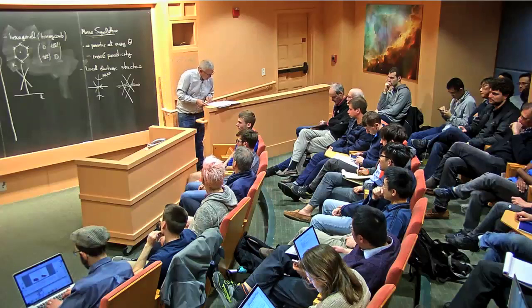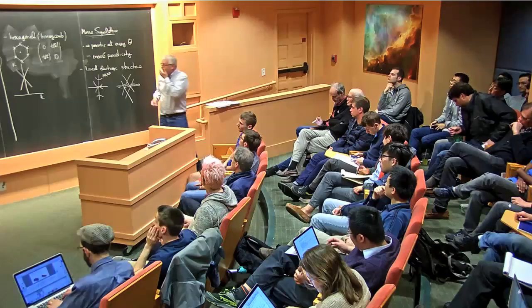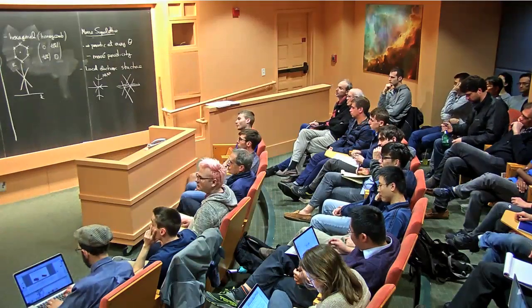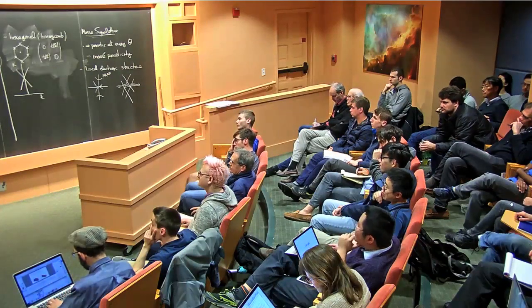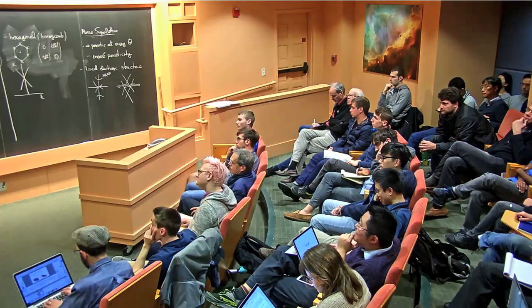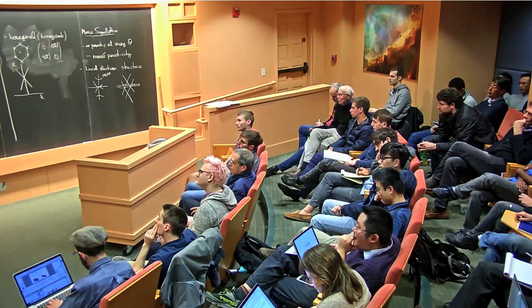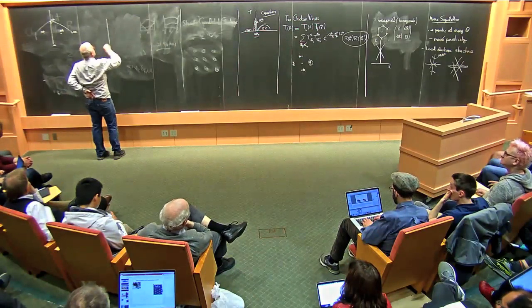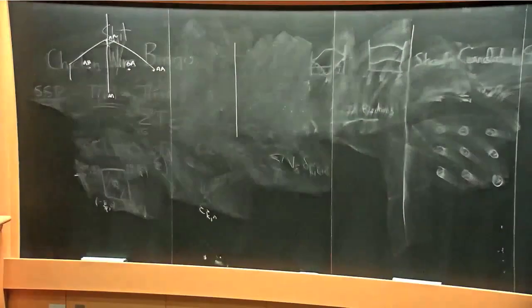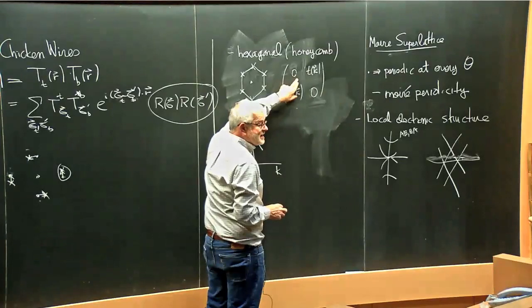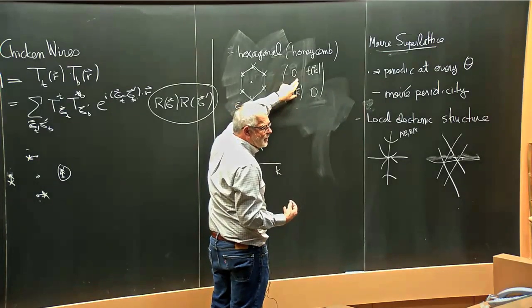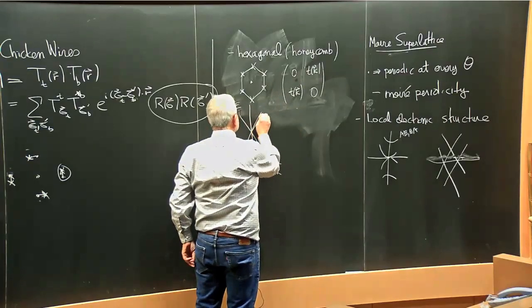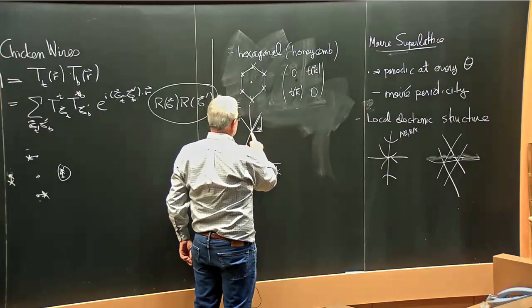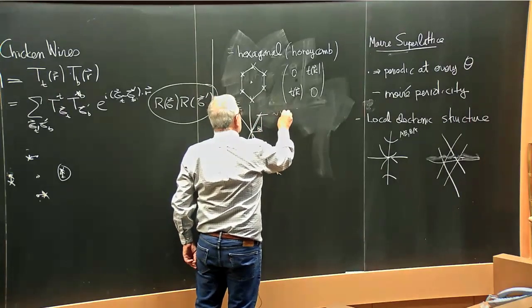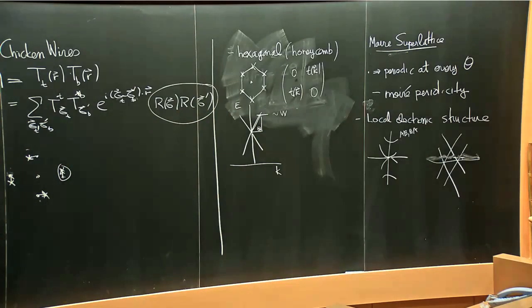Okay, so I'm just going to make one more point, and that is the bingo of all of this. The electron waves in these Moiré superlattices are, as you can imagine, kind of interesting, and there was a literature connected with them. It was discovered that at a certain twist angle, where the Moiré periodicity is connected to a momentum boost when you go from one layer to another, and when the size of the momentum boost Q times V, this energy, is approximately equal to the interlayer tunneling energy, when the layers are strongly coupled together, then that's when something special happens.